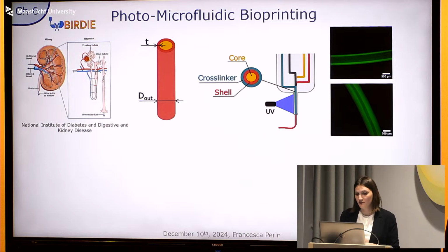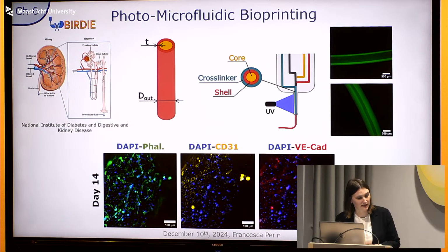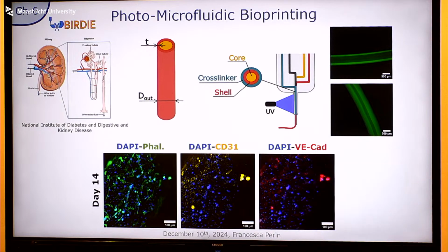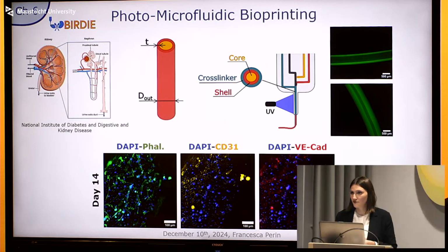So after achieving more or less control on the size of the fibers that we could print with these cell-free experiments, we moved on to printing with cells. And here is an example of HUVEC printed after 2 weeks. What you see here is the surface of one tubule in which the HUVEC formed a sort of monolayer. And you see that we had a very good distribution of CD31 and VE-cadherin, which is a good sign of tight junction formation from endothelial cells.